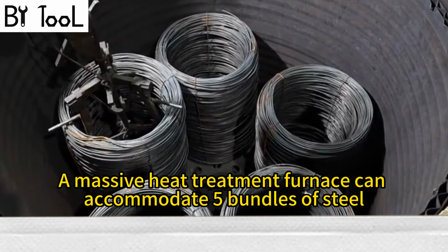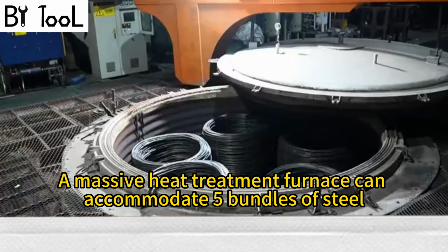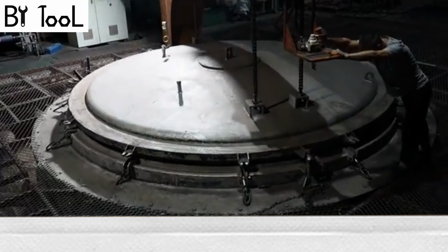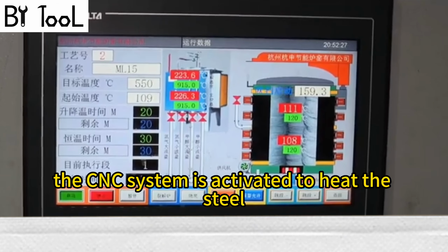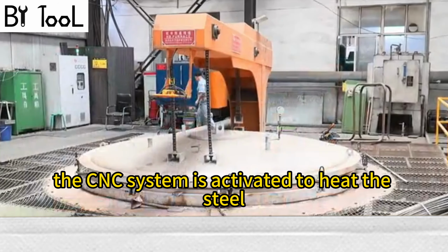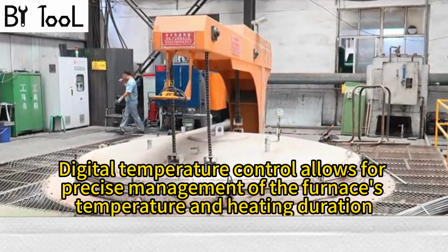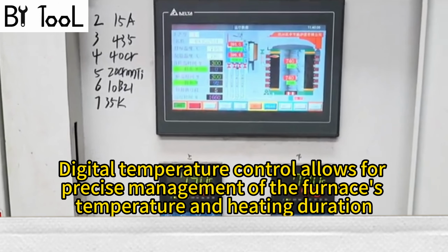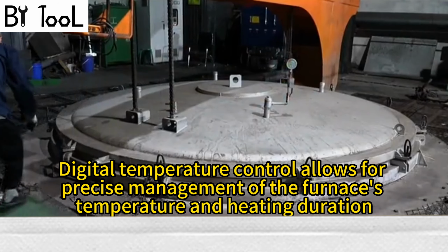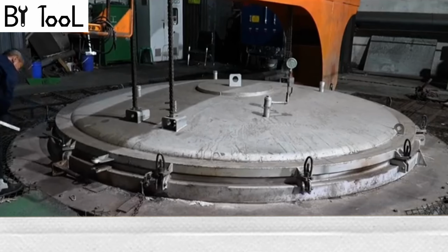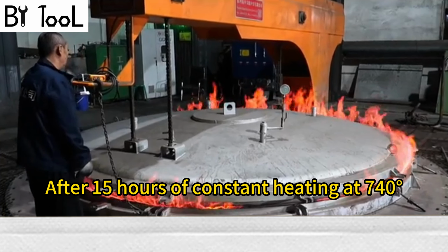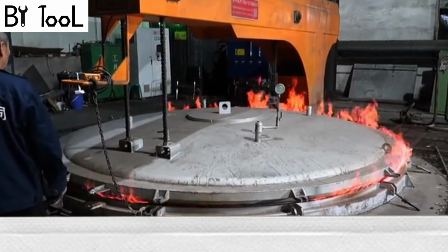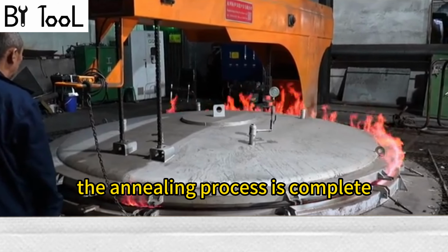A massive heat treatment furnace can accommodate 5 bundles of steel. Once the furnace is sealed, the CNC system is activated to heat the steel. Digital temperature control allows for precise management of the furnace's temperature and heating duration. After 15 hours of constant heating at 740 degrees, the annealing process is complete.